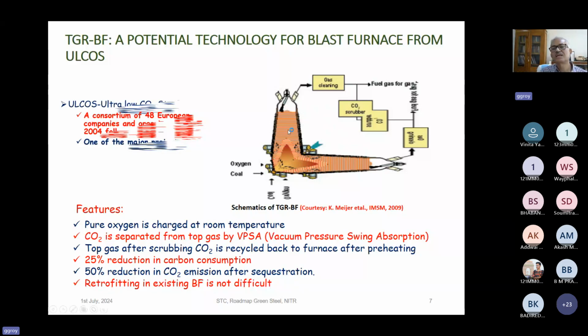The idea here is that since you are replacing the air by oxygen, the top gas is only CO and CO2. There is no nitrogen dilution. After gas cleaning, you can scrub all the CO2 from the CO-CO2 gas mixture, take out the CO2, and then inject the CO from the bottom of the furnace. This is called top gas recycling. Basically, you take out the top gas, scrub the CO2, and after preheating, inject the CO again into the blast furnace. That will improve its carbon efficiency.